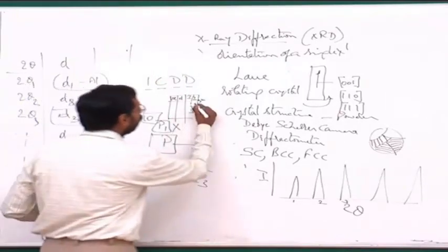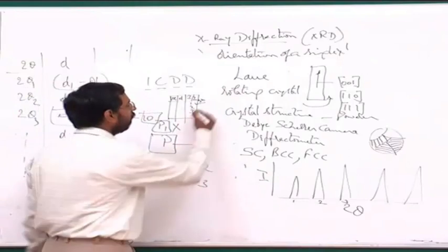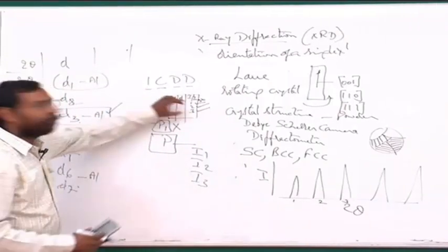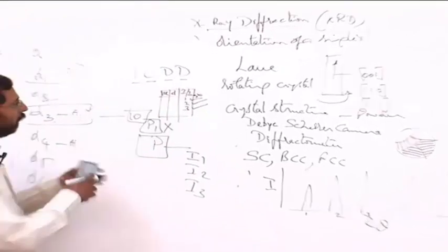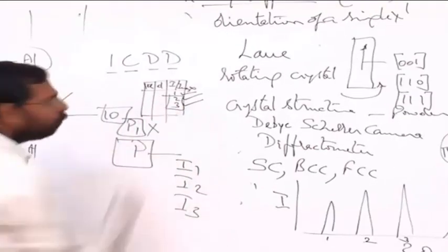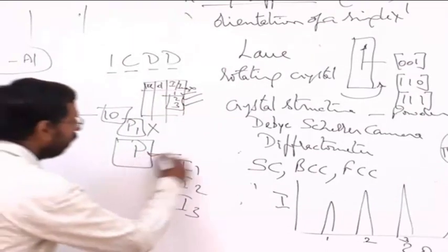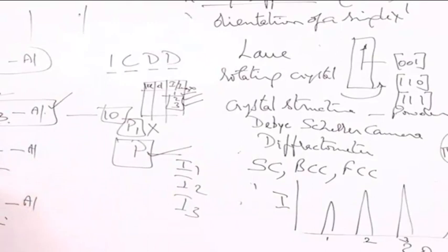What is more important is I will look at the most intense, the second most intense and the third most intense, and look at whether these 2 peaks are also there in our XRD pattern. If they are there, then I say this phase is there. If they are not there, I say no, this phase does not exist in my material.